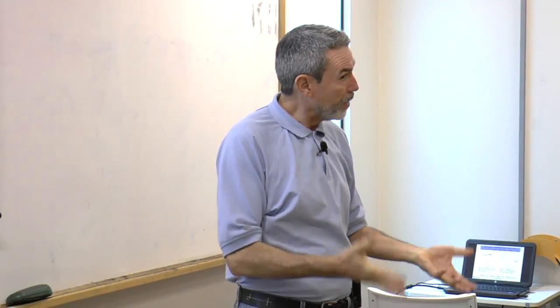So our conclusion, there are many, many more plots and other works that we did, but the conclusion is that the metastable phase appears, but does not explain the discrepancy between the theoretical value and the experimental value. And there are studies for other systems too. I'm just giving one example here to you.